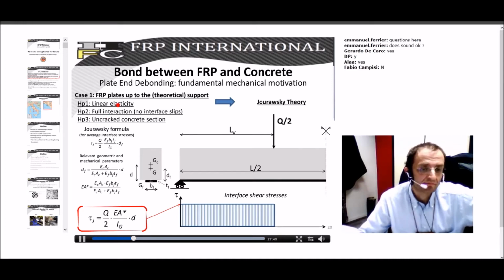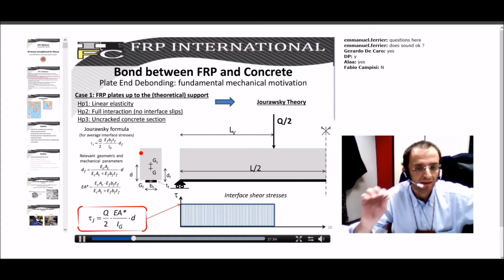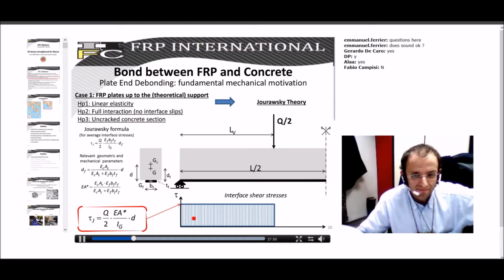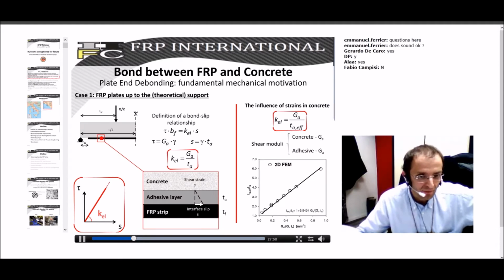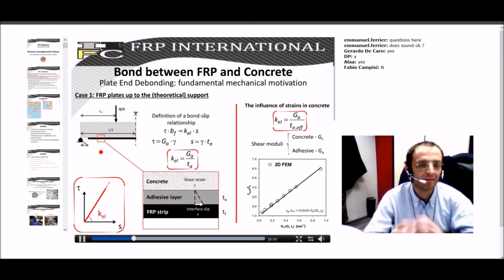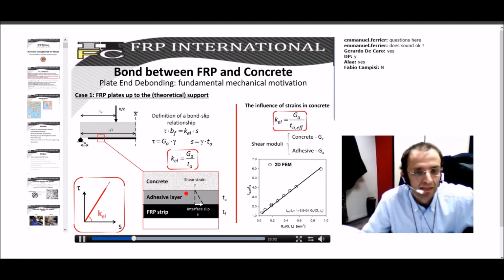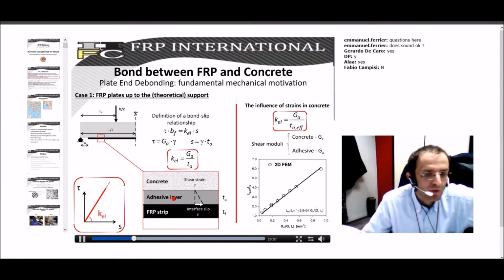But as we said, full interaction is not a realistic assumption. As you will see here, we have a layer between FRP and the RC beam. We have a layer made of an adhesive, typically made of an epoxy resin. So we have a flexible layer which is characterized by certain elastic properties, and especially by a shear modulus. GA is the shear modulus of this layer.